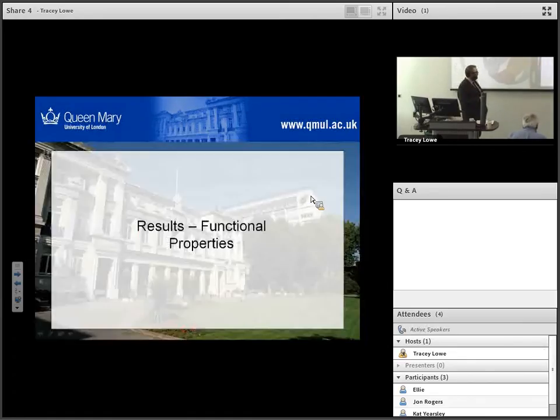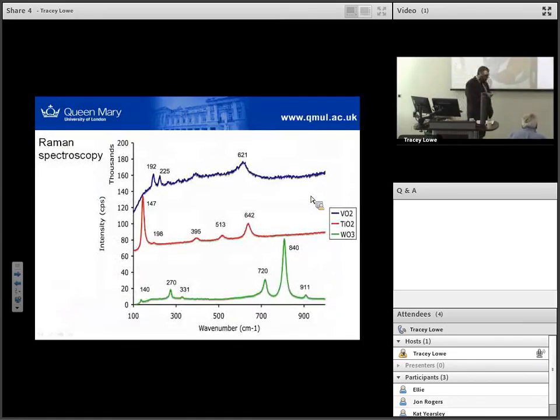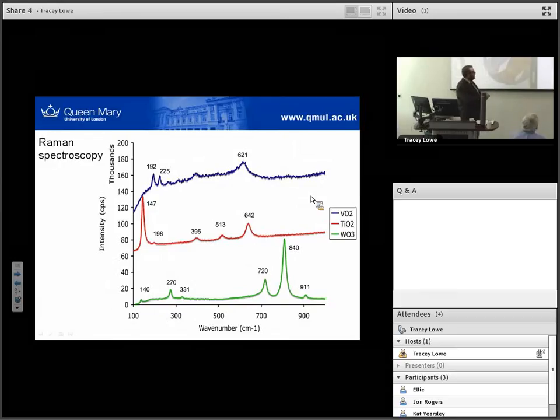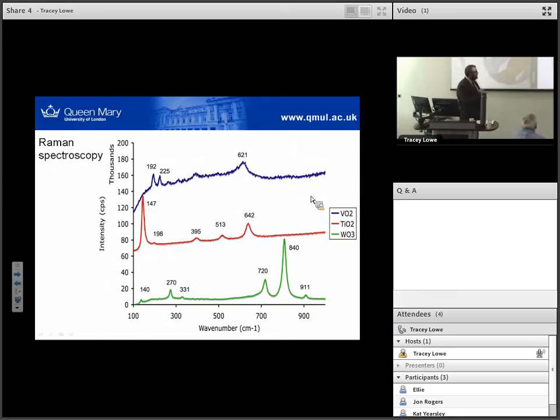Just some Raman spectroscopy to show that we do in fact get the phases we want. The titania corresponds to anatase, and for the tungsten oxide, that's quite nicely monoclinic tungsten trioxide.